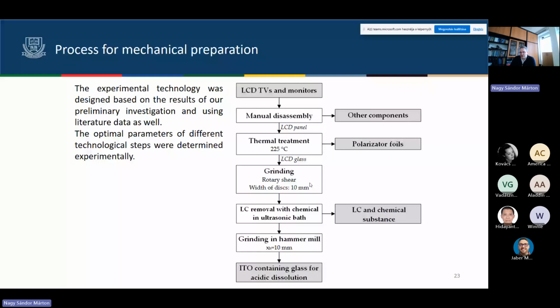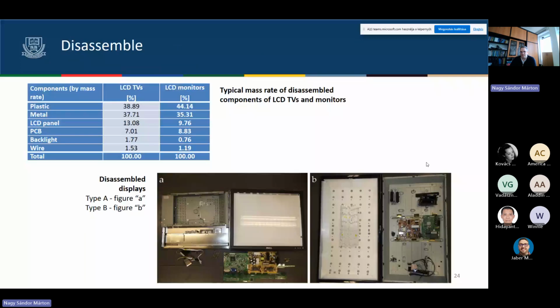The mechanical preparation technology was the following. The LCD displays were manually disassembled, and the LCD panel itself was thermally treated to remove the polarizer foils. After that, there was a grinding process, and with ultrasonic and chemical baths, the liquid crystal was removed from the inner surface of the glass. After that, there was grinding in a hammer mill below 10 millimeter, and after that, there was an acidic dissolution, and so the acid was able to remove the valuable indium tin oxide layer from the surface of the ground glass. And after that, of course, precipitation was made, which generated the valuable materials. You can see here the composition of these TVs. You can see this one, for example, what I mentioned, a quite large piece of iron is there.